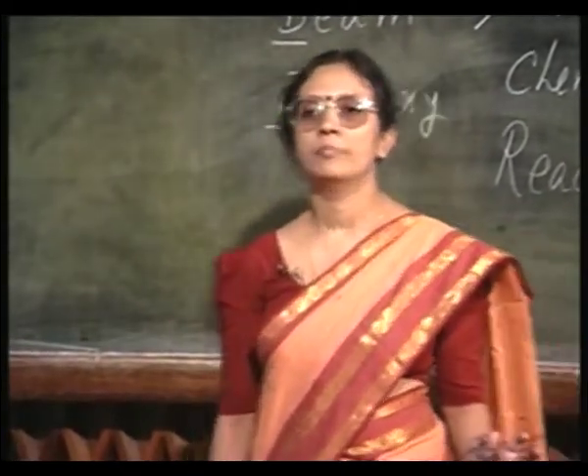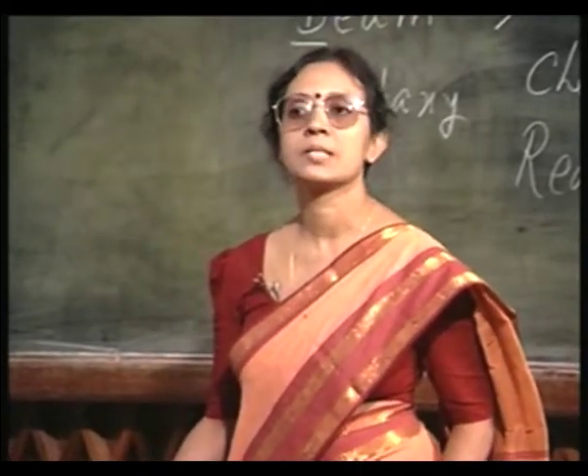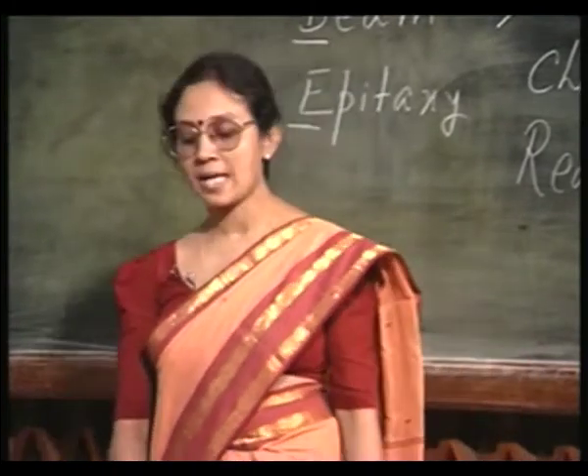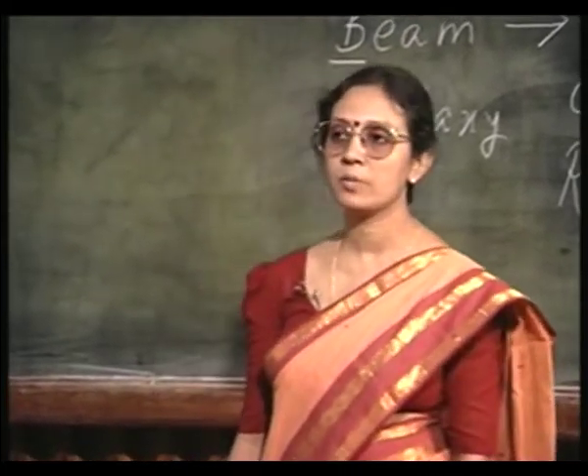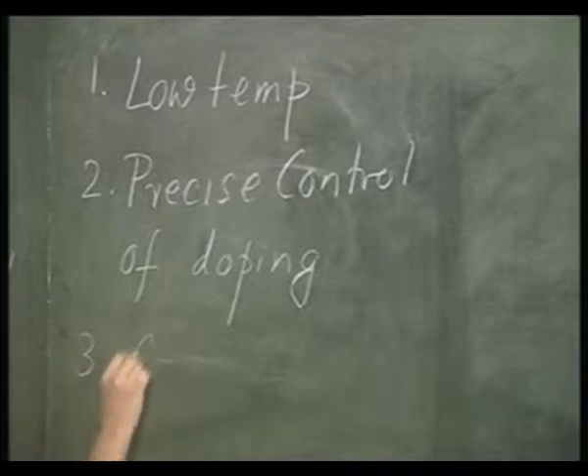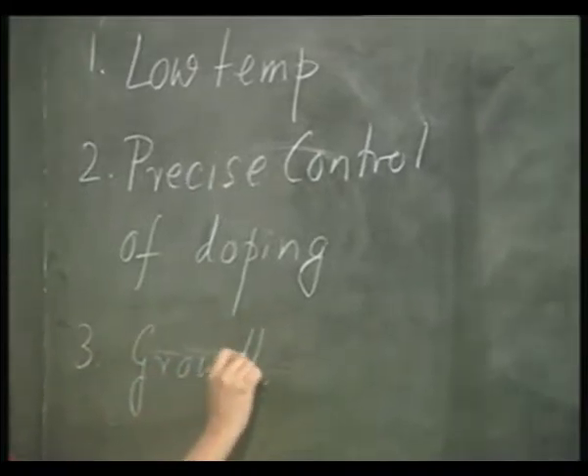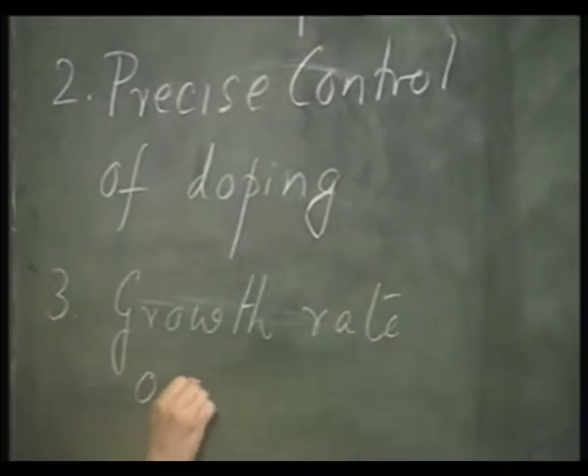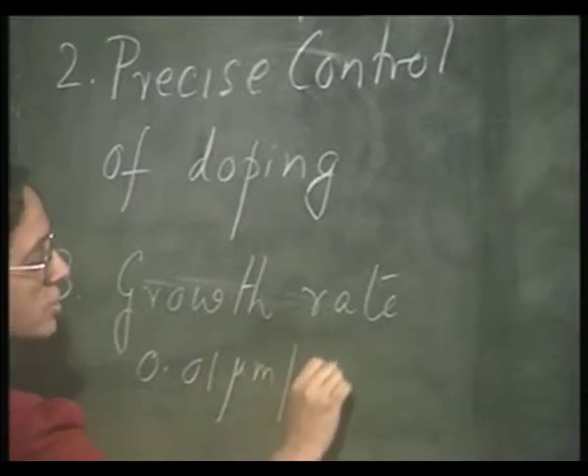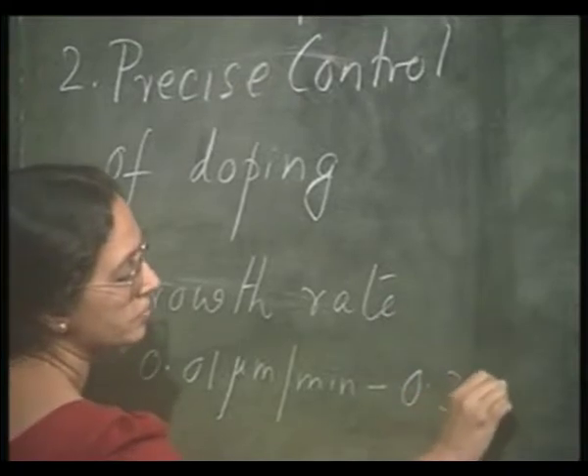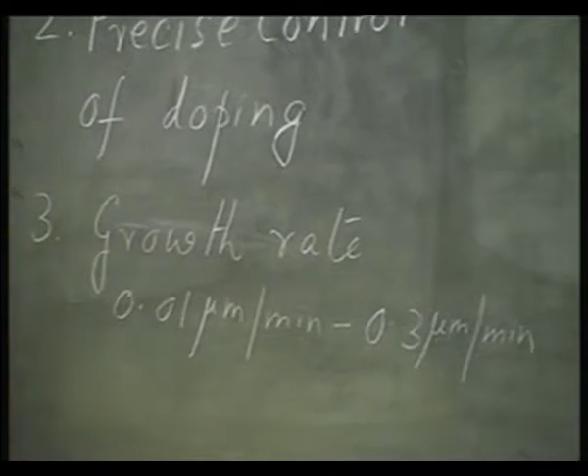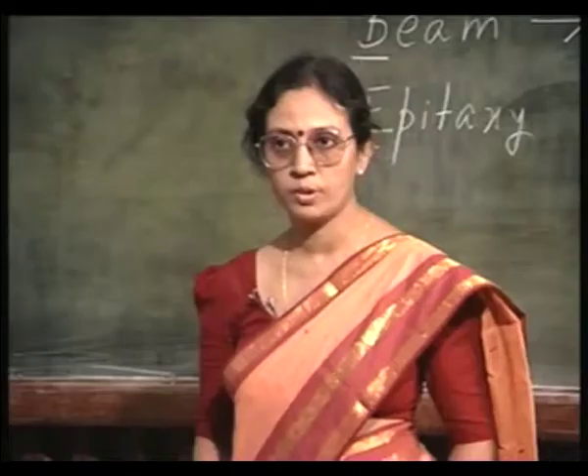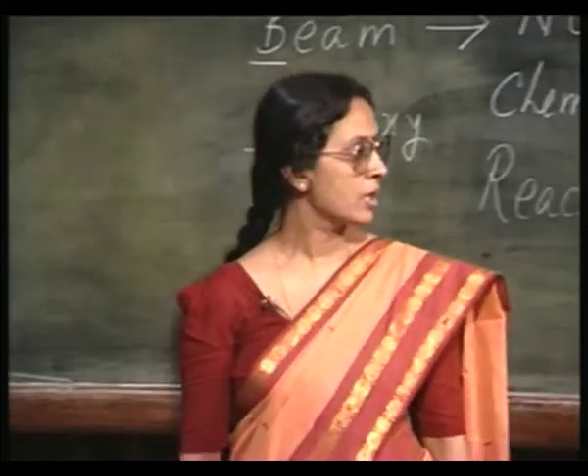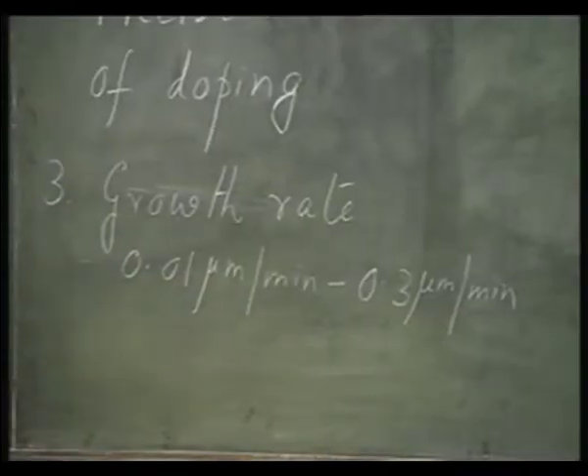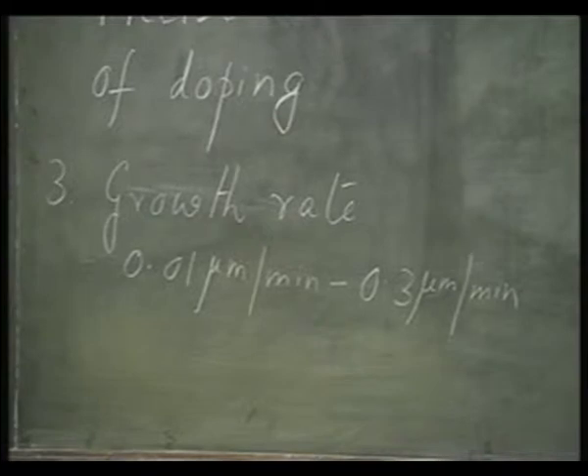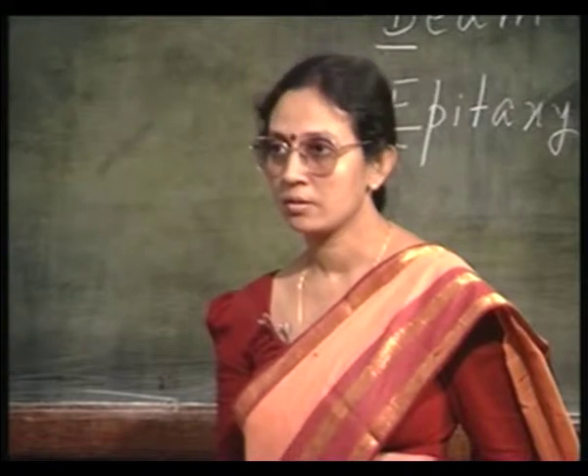MBE is also, the growth rate can be more precisely controlled. You can achieve a growth rate as small as 0.01 micrometer per minute, up to say 0.3 micrometer per minute. So, depending on how thin or how thick you want your epitaxial layer to be, you can control the growth rate. I would like to draw your attention to the lower end of the epitaxial growth rate. It is 0.01 micrometer per minute, that means 100 angstrom per minute, very precise control.